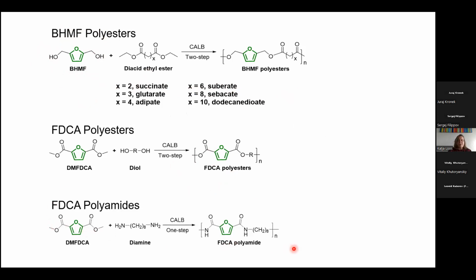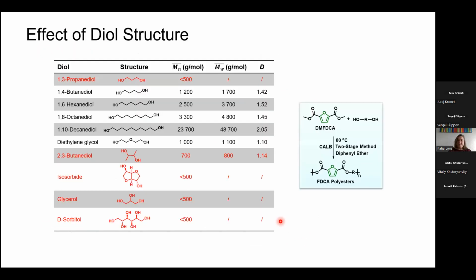And we also did polyamides, which also works very well. And so we are still also busy with that, because this is a big playground. And for instance, if you just have Calb, a commercially known enzyme, it takes a lot of FDCA and a lot of flexible diols. But for instance, if you would like to do an FDCA isosorbide polyester, it doesn't work properly. It's too bulky for the active site.